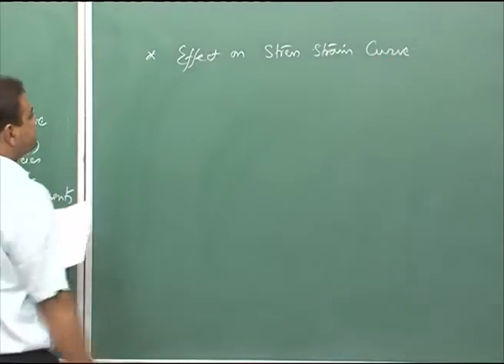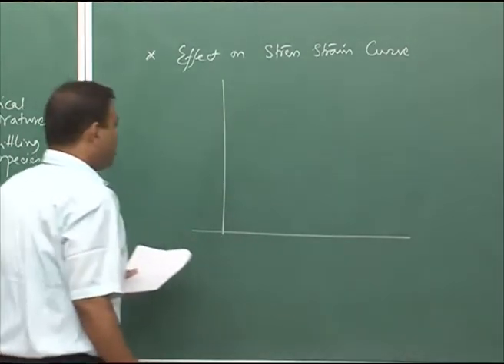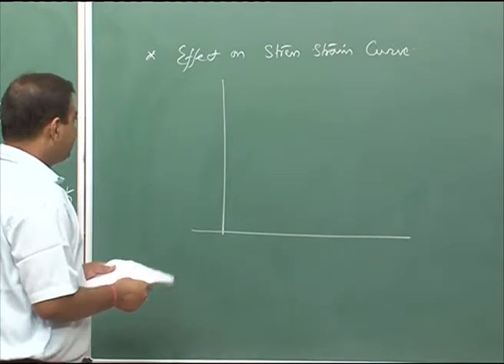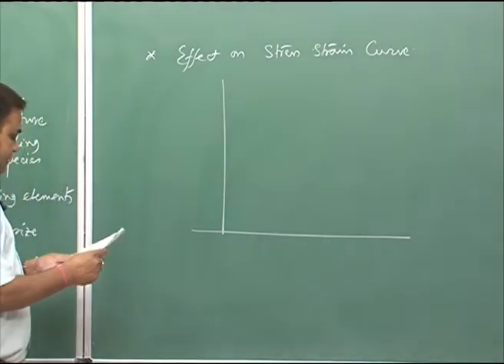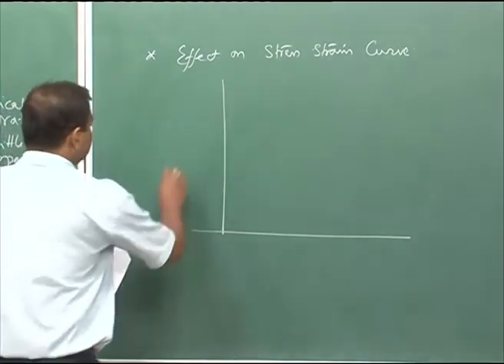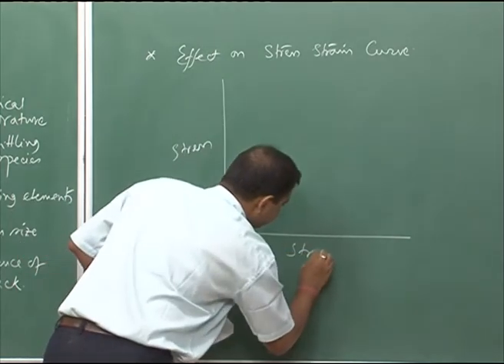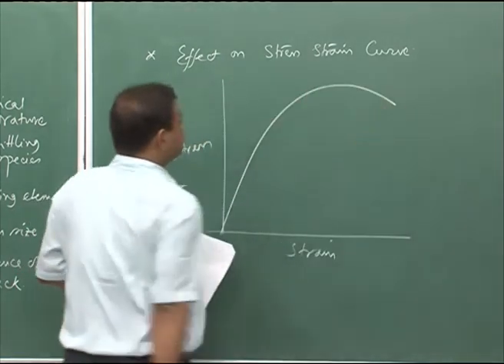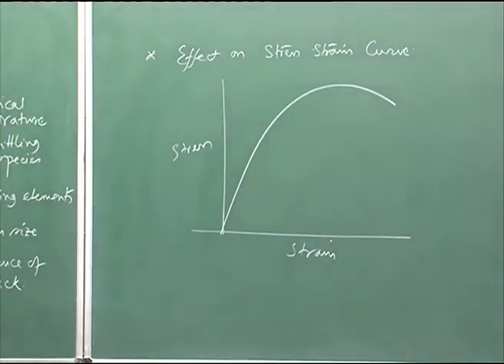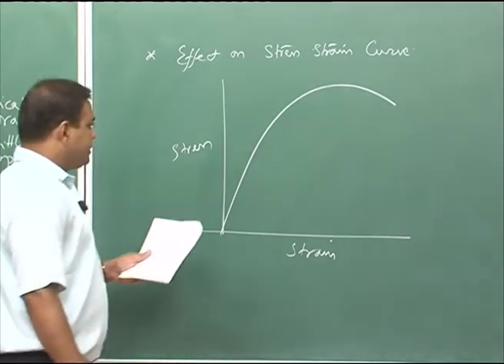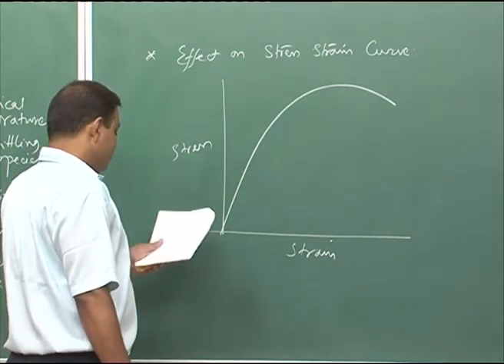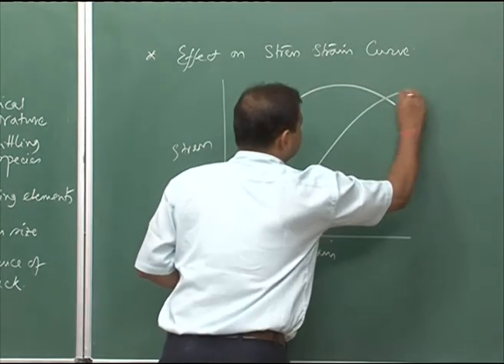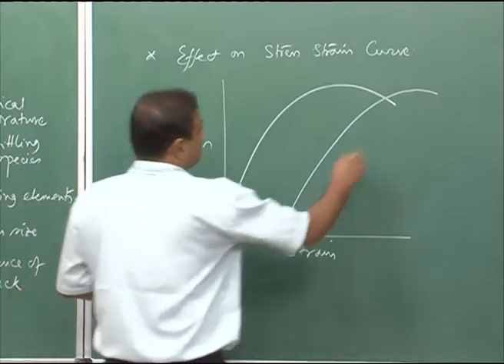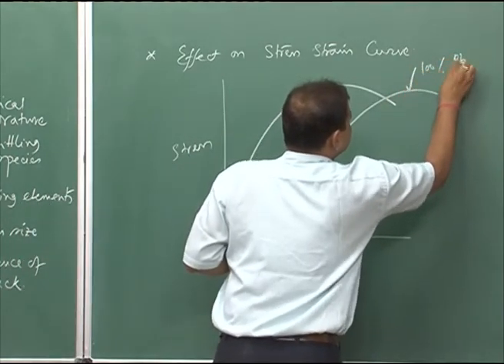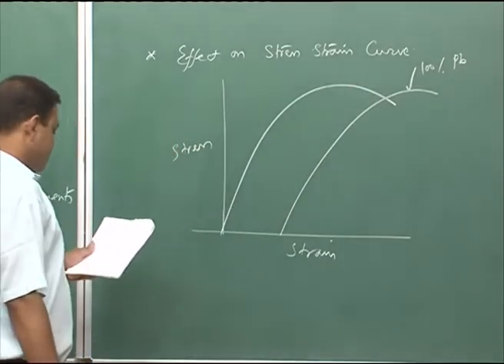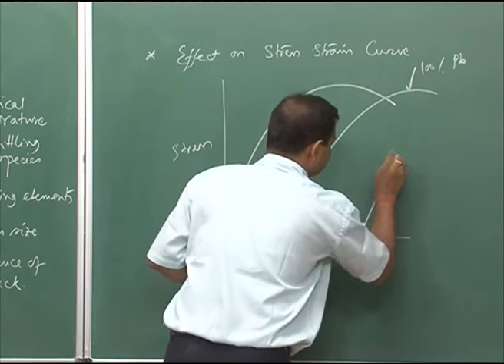So, for example, one such example is in case of copper. If we want to see what would be the embrittlement effect in the presence of bismuth, then this is stress, this is strain, and if it is uncoated, that means without the presence of any liquid metal, you have the characteristics like this. And if it is 10% lead, then you can have the character like this. This is in case of 10% lead, and if you consider 100% bismuth, the nature would be like this.